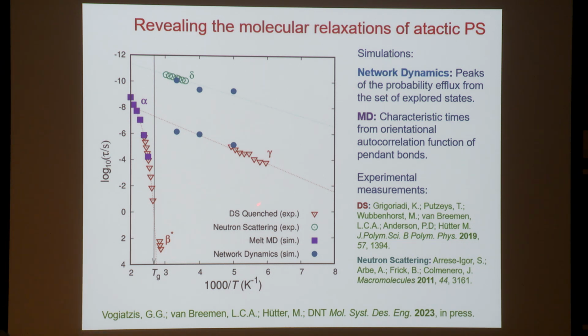And it seems that they are representative of what the experimentalists call gamma and delta subglass relaxation transitions. These are accessed by dielectric spectroscopy and also neutron scattering experimentally. In the same plot here, we show what happens in the melt state at high temperatures. Here we have again relaxation times, these purple symbols that were obtained by direct molecular dynamics by looking at the reorientational motion of phenyl stems in the melts. And they give us a picture of the alpha or main relaxation transition.